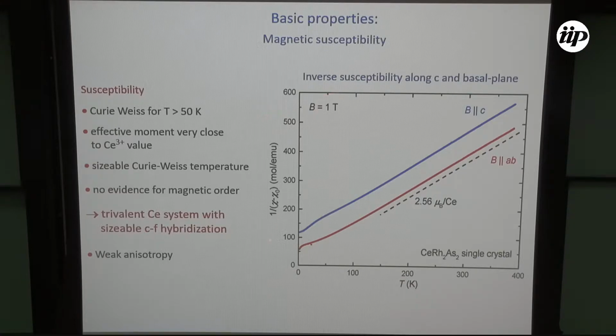This is the inverse susceptibility as a function of temperature along the c direction and in the basal plane. And you see a very nice Curie-Weiss law. The slope is exactly, or very close to, what is expected for trivalent cerium. And therefore you know you have essentially a trivalent cerium state. But the Curie-Weiss temperatures are quite sizable, and there is no evidence for magnetic order in those data down to 2 K. That is an indication that we have a trivalent cerium system, but with a sizable hybridization. Also, the anisotropy is comparatively weak if you compare, for example, with YbRh2Si2 or with CeRu2Si2.